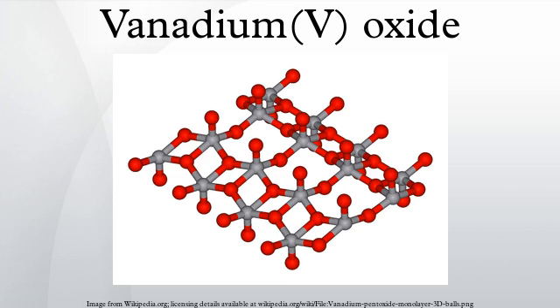Vanadium oxide is produced when vanadium metal is heated with excess oxygen, but this product is contaminated with other lower oxides. A more satisfactory laboratory preparation involves the decomposition of ammonium metavanadate at around 200°C: 2NH4VO3 → V2O5 + 2NH3 + H2O.